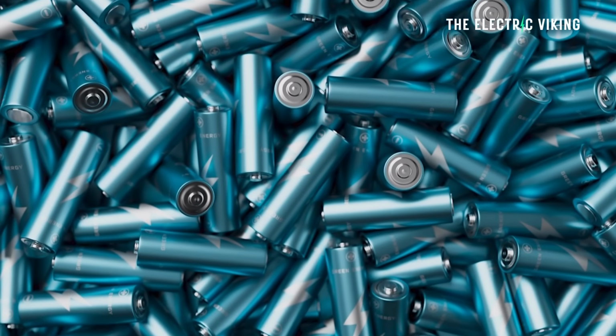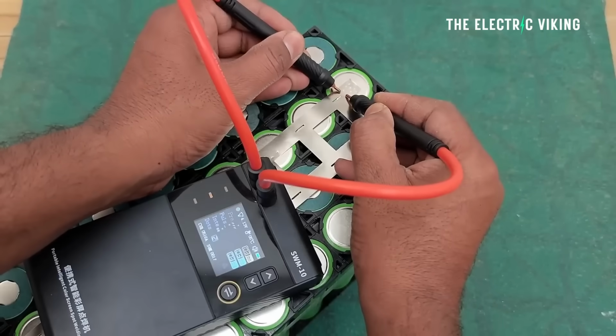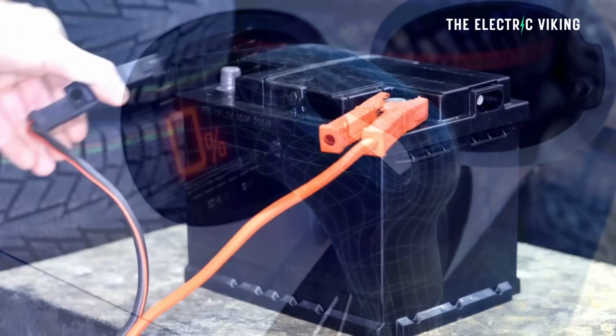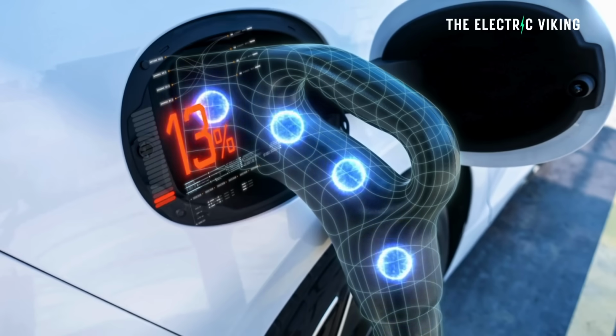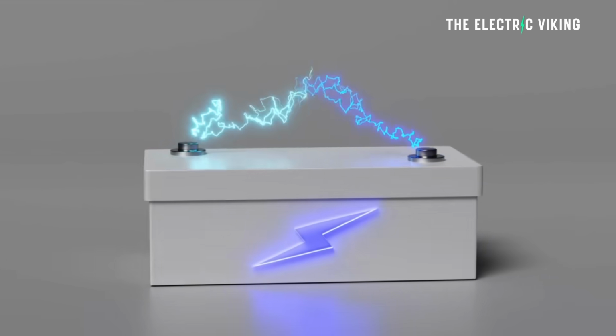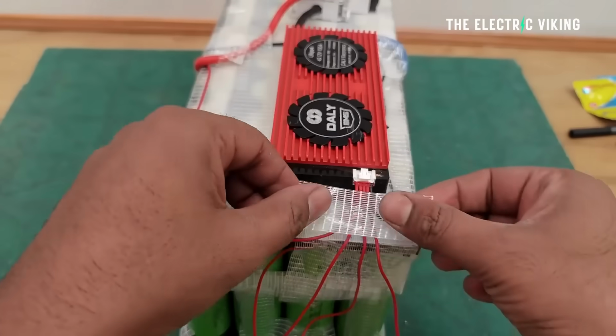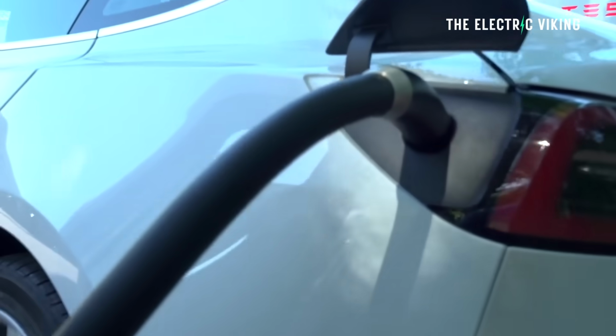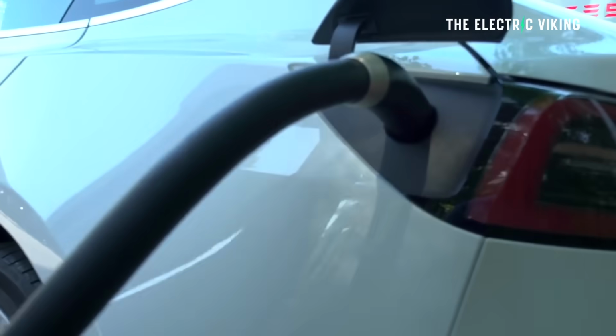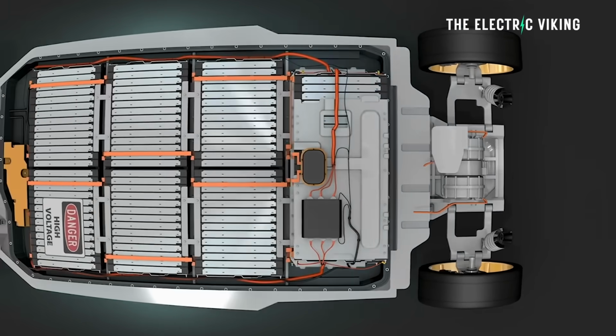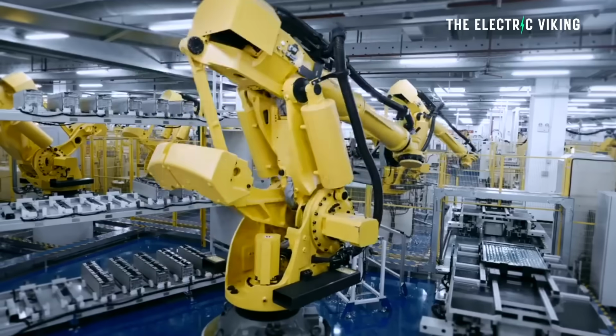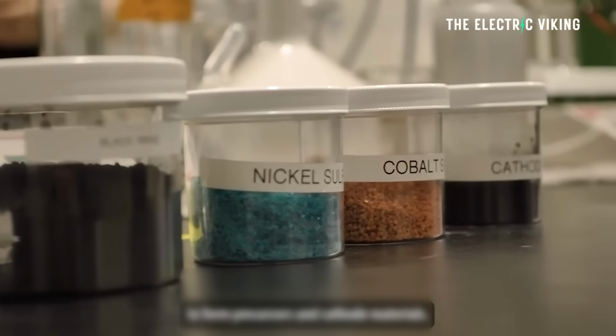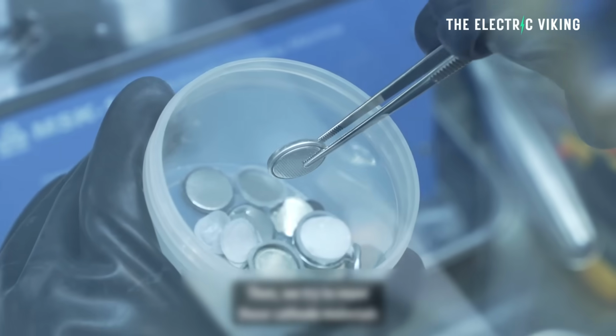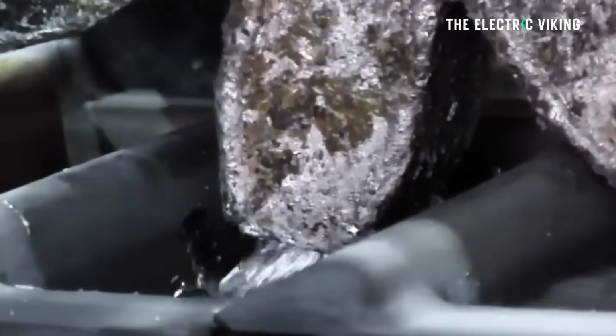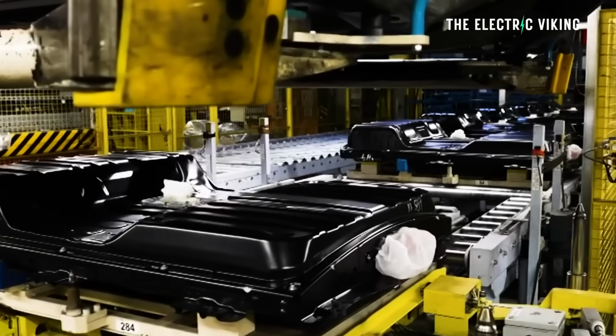Full battery cells using this material were able to complete more than 300 charge-discharge cycles while still retaining 80% of their initial capacity. In addition, symmetric cells, which are used to study the stability of the electrolyte itself, operated for more than 500 hours without any battery degradation. Now, apparently, this is the first demonstration in the field which showcases this kind of long-term stability. At the same time, though, these researchers created a safe and scalable method for recycling highly reactive lithium metal anodes.